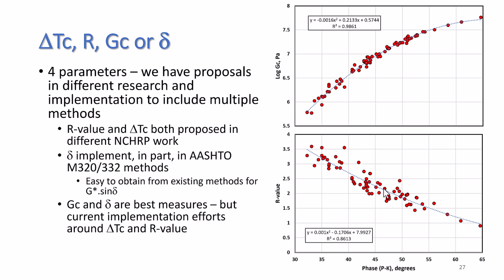We never have a measure down at 1e to the 9. So we're always doing a certain amount of extrapolation. And when you're fitting a curve, it's very sensitive to any minor deviations or shape in that curve. So since we can measure the phase angle quite easily at a constant modulus, and we can measure the crossover modulus, these are both values that we measure. They're within our measurement region. There's a high degree of correlation there.